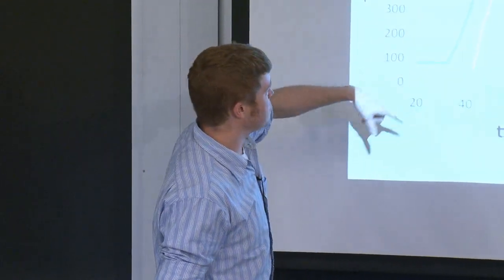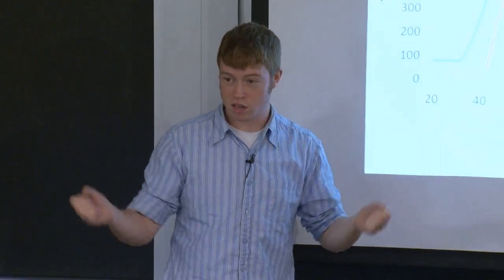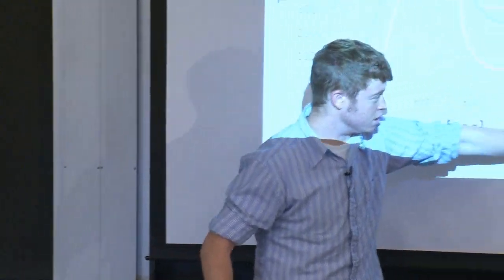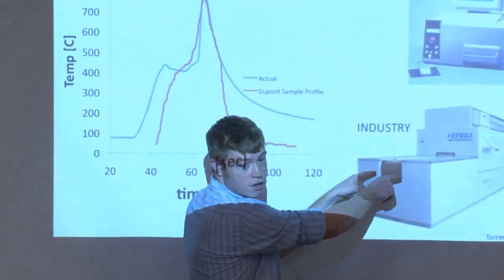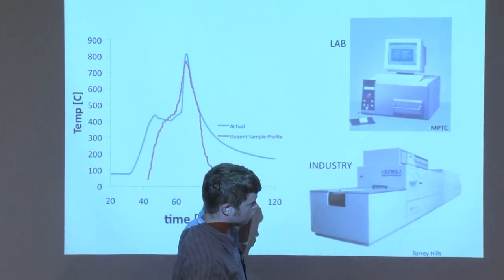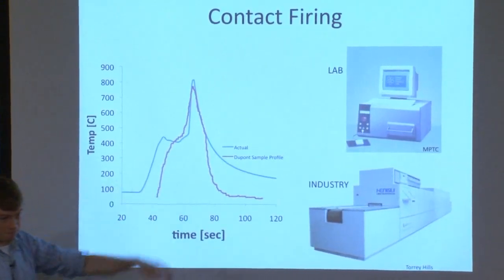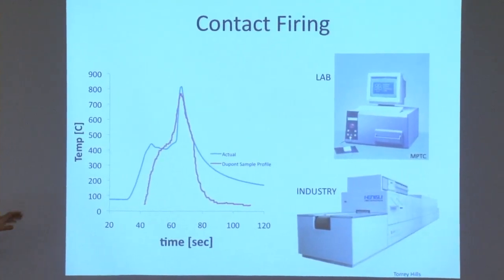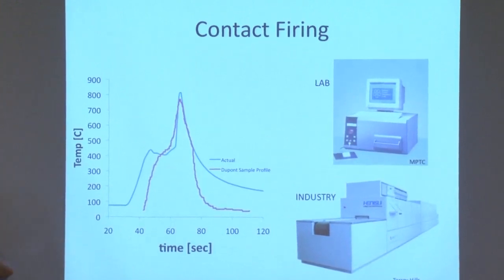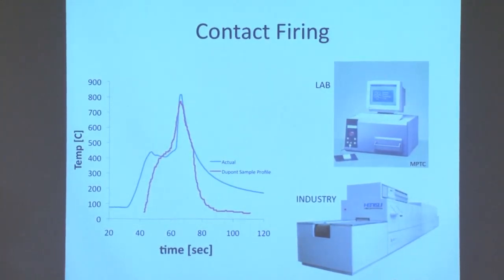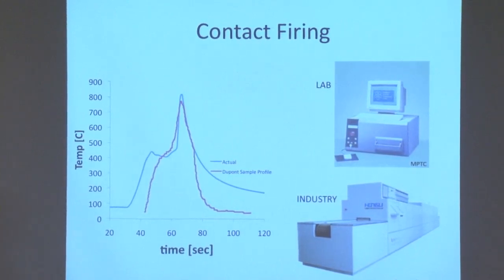So anyhow, it's done in an oxygen atmosphere, so they generally force airflow into these giant belt furnaces. And these are really long. That's probably about a foot wide, maybe 18 inches wide, and it goes on for tens of feet, or several meters, depending on where you're from. It's done in an air atmosphere because it needs to burn off a lot of the binders and some of the organics that might still be there. Those organics burn off, and what you're left with are the little metal particles, the frit, and some metal oxide glass. It's usually lead oxide, although DuPont will never tell you, but from papers I've read, this is generally what's used.